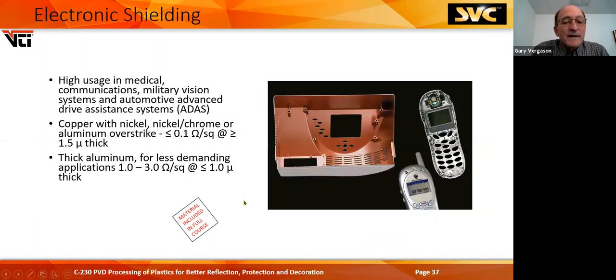Very, very high use in medical communications, military vision systems, and automotive advanced driver assistance systems, your self-driving cars. It shows a couple of different coatings here. You can have thick copper coatings with a nickel chrome or aluminum overstrike to protect the copper from corrosion, usually 0.1 ohms per square at a little bit more than 1.5 microns thick. Thick aluminum coatings, like on the phone here, are much less demanding in application. Usually those specs are 1 to 3 ohms per square, around a micron thick, and can be done pretty quickly.